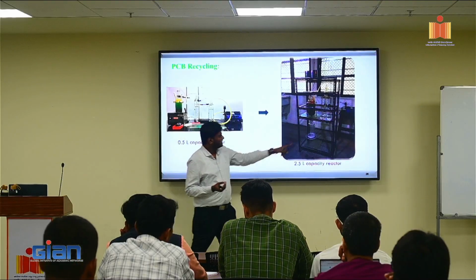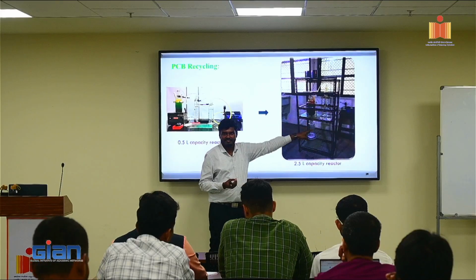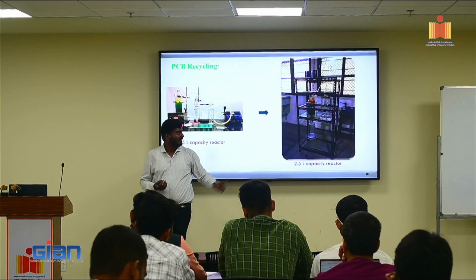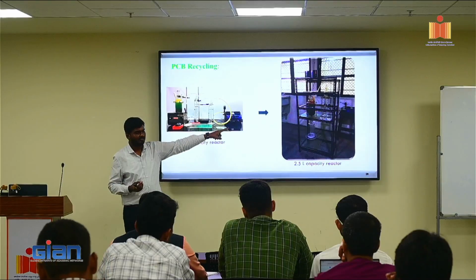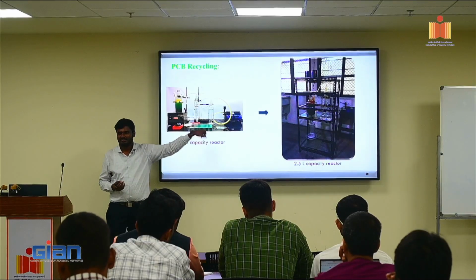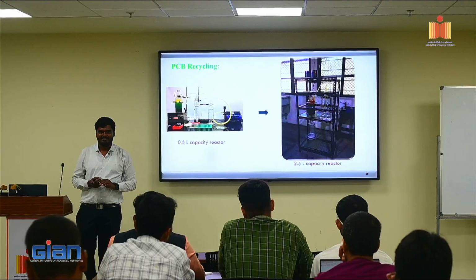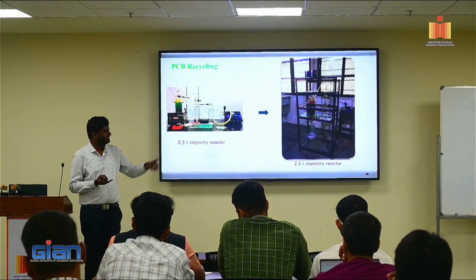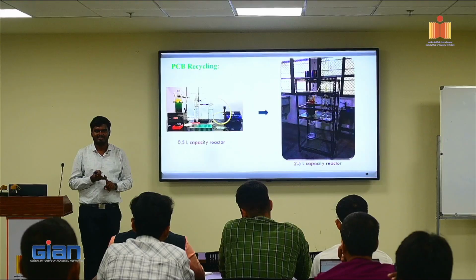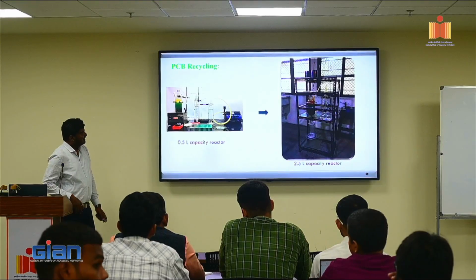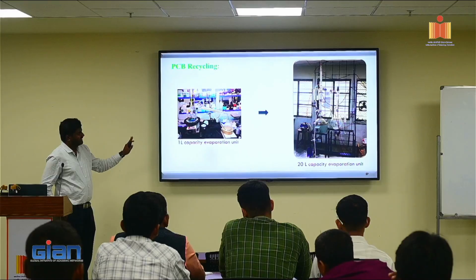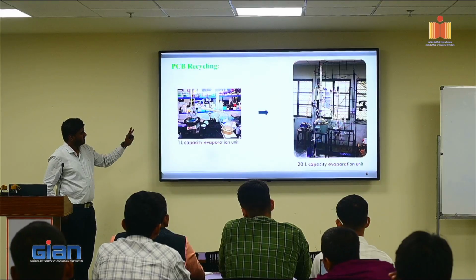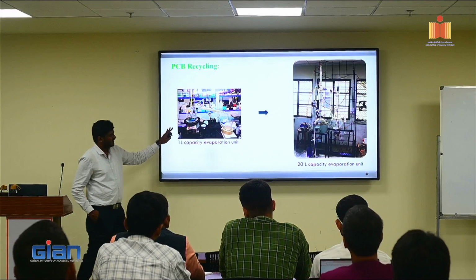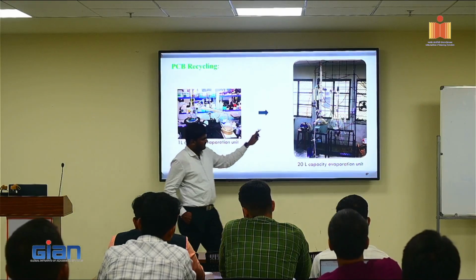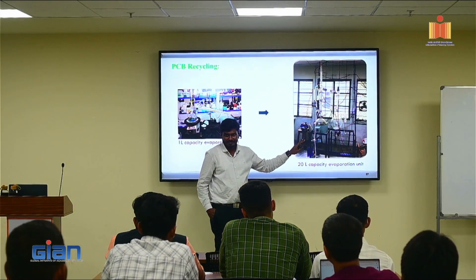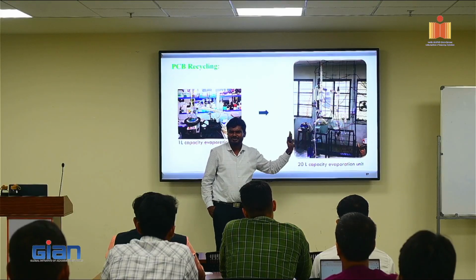And when I open this valve after 1 hour, all the liquid solution gets collected at the bottom, and it is also connected to a big absorption column. So we got to know what size I have to maintain, and we collected it. So we are collecting NOx gases and we are getting colloidal solution exactly after 1 hour. So this was done. Similarly, this is for lead nitrate evaporation. So we used some evaporation. So this was 1 liter capacity. Then we went for 20 liters capacity. This taught me so many lessons.